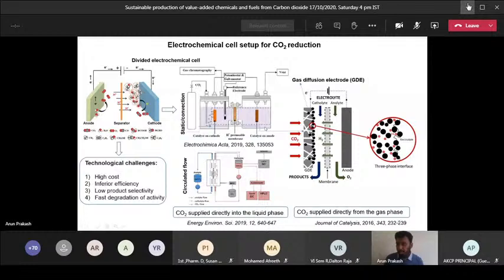And also depending on the pressure. Normally it is one atmosphere pressure, right? But when you do this reaction in a closed cell and control the pressure, and also change the electrolyte, you don't need to use a higher concentration of electrolyte. In this case they use potassium hydroxide. If you see the black curve, that is for 1 molar potassium hydroxide.